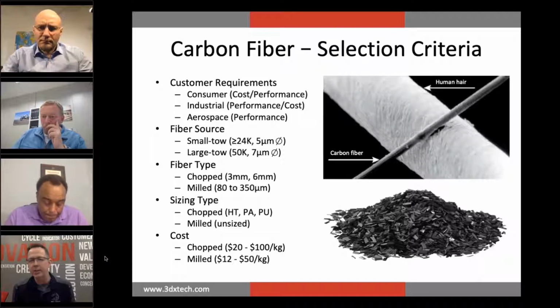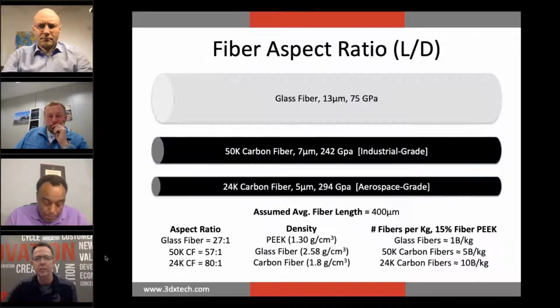Chopped carbon fiber ranges anywhere from $20 to $100 a kg, depending on the source and the end use. And milled is, of course, less expensive, and it's typically $12 to $50 a kg. The reason I bring this up is all these considerations have to come into play when people are specifying a carbon fiber for a given end-use application. We have grades that cover the gamut on all these. And so I just want to make sure that carbon fiber, it's not just carbon fiber. And it's why I put this slide together also, which kind of explains a little bit of what we do and why we do it.